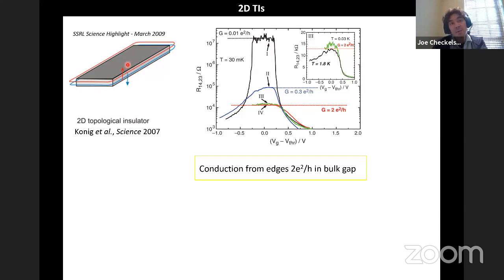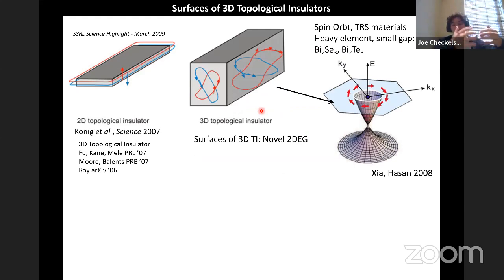You had a 2D insulator with a boundary mode, and that was detected in this case by measuring the conductance of this system and finding that under the right conditions, when the material was grown in the right way, when you would tune some tuning parameter to the condition where you should only have these edge modes, you found indeed you had some quantization of the conductance. But again, and I think this is a real hallmark of this subfield, from one idea come many related and beautiful concepts. It was soon realized that if you could do that in 2D, why not do something similar in 3D? And in that case, you would have a 3D insulator, this kind of bulk insulator, but it's wrapped with an interesting kind of 2D mode on its surface.